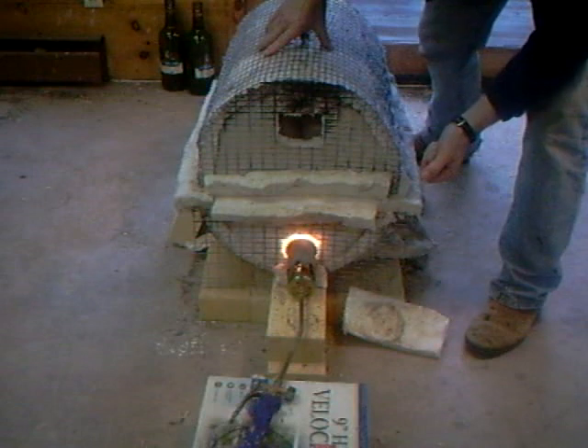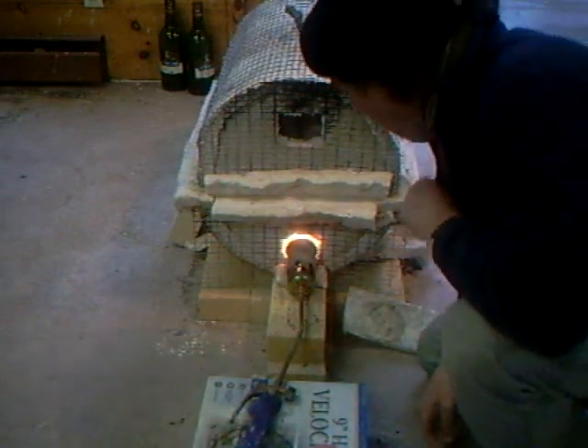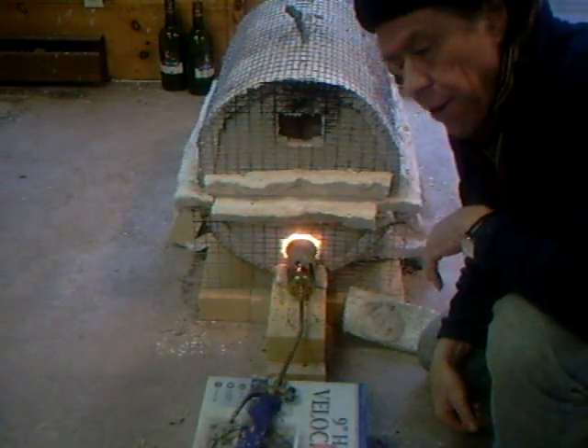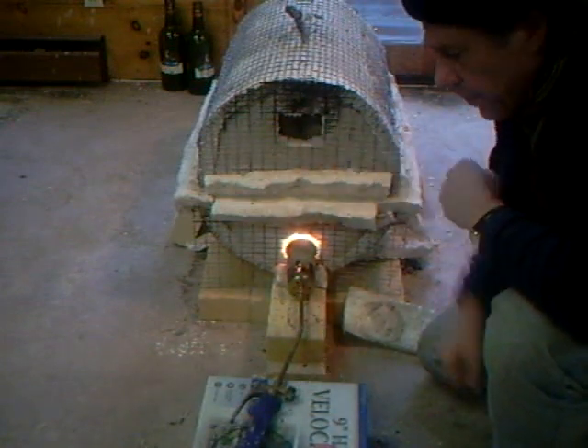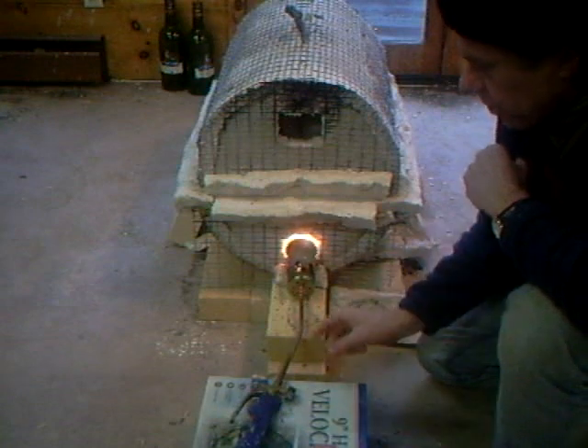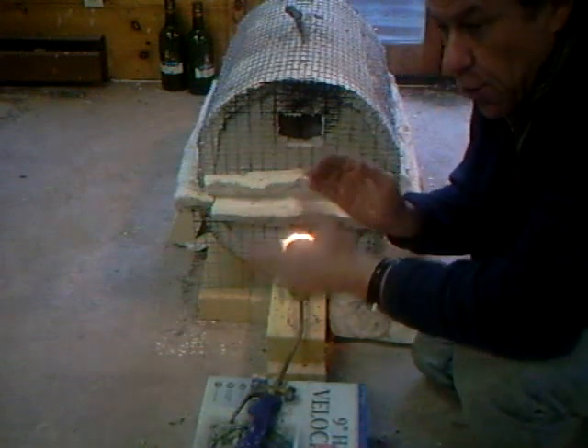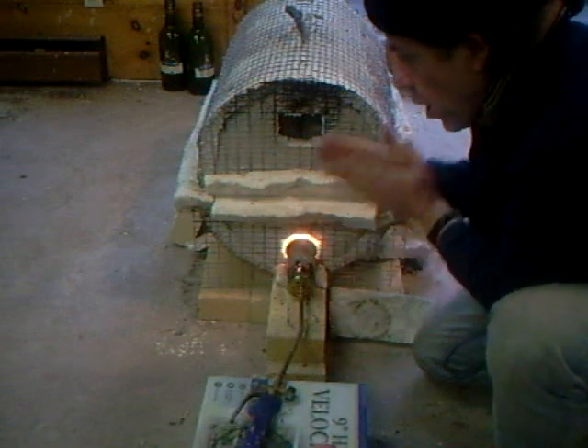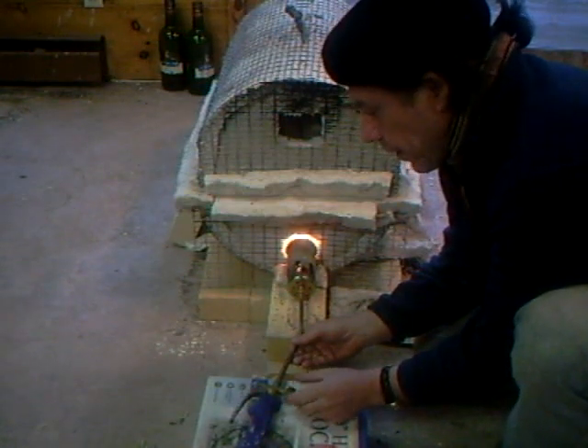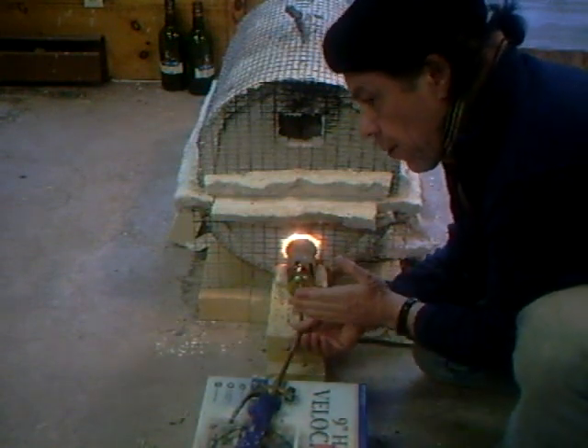We're going to start very slow like this. Low, medium and high. The next question is: how long are we going to have it on low? Well, I would say probably put it on low for a good hour to allow the pots to warm up. It can depend on the pots a bit — if you're a bit suspicious, no harm in giving it a bit extra time, maybe an hour and a half. Within the realm of low, you could have low, medium and high. So at the moment we're in low low — the lowest of the low. Shortly I'm going to start turning it up very slightly to medium low, and then it'll be high low, but it'll still be all in low.